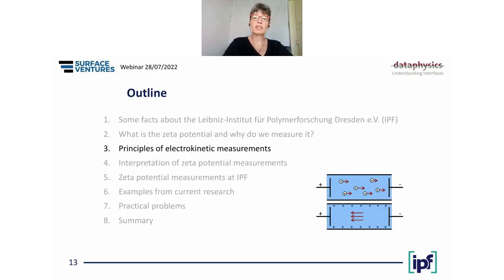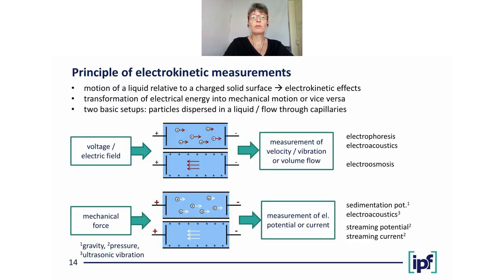So how do we measure the Zeta potential? For this purpose, we use the so-called electrokinetic measurements. Electrokinetics means we have a motion of a liquid relative to a charged solid surface. Then we get the so-called electrokinetic effects. That means we have a transformation of electrical energy into mechanical motion, or vice versa, depending on the experimental setup. We have two basic setups depending on what we want to measure. Either we have particles that are dispersed in a liquid, or we have a flow through thin charged capillaries.